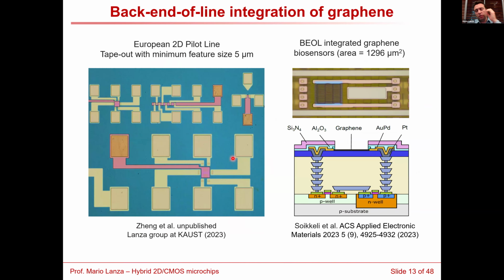There are other examples, more recent. This is a paper very recently published in which the authors fabricate biosensors transferring graphene on a pre-patterned silicon microchip. You see here the graphene plays the role of conductive paths between these 2 wires, where it can be functionalized to detect different kinds of biochemical species. And here the area of the graphene is also quite large. So this is also low integration density.